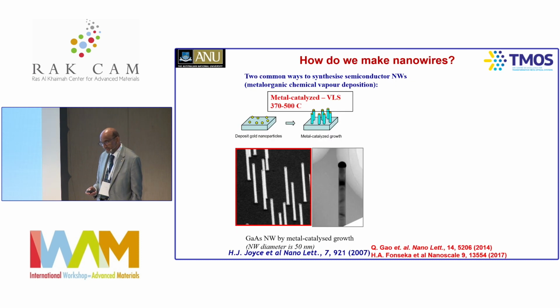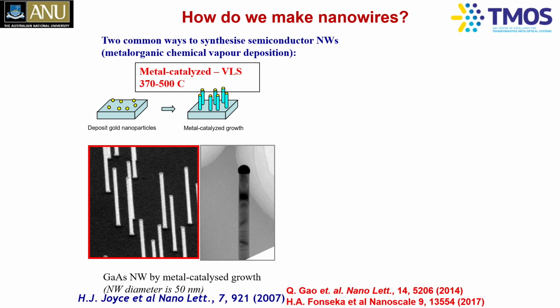If nanowires are of so much importance, how do we make them? There are 2 main techniques we make use of. One is called the VLS growth process, a metal catalyzed technique. In this case, we take nanoparticles of gold, for example. We put a droplet of that on top of a semiconductor, whether it's silicon or gallium arsenide. And then typically we use MOCVD, metal organic chemical vapor deposition. This is a technique which is used by industry, and it is a scalable process. There's also an alternative technique called molecular beam epitaxy. We can make use of that technique as well.